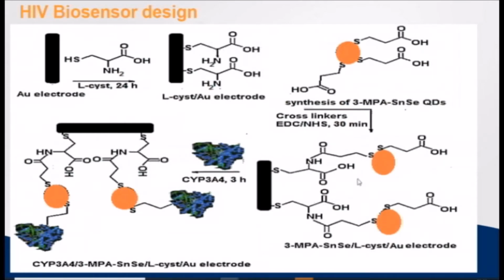Now, because we have activated these groups, some of the functional groups from the quantum dots are still free, since we have attached the carboxylic group onto the amino group, and they are still activated and free for the attachment of the enzymes. Enzymes also have amino groups and carboxylic groups. So we can now take these functionalized quantum dots and attach the enzymes onto the quantum dots modified electrode to form our biosensor system.